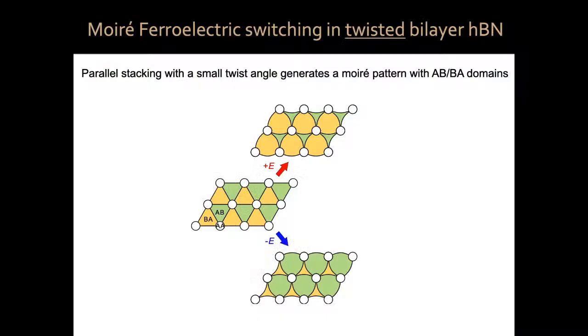If I twist them by a small angle, I can realize actual Moire ferroelectricity, where now, when I put a twist angle, I'm going to have these AB and BA domains similar to magic angle graphene, except that these now are very different. They have opposite electric dipole moments, those domains. And if I apply an electric field in one direction, I'm going to increase one type and shrink the other. And if I apply it in the opposite direction, I'm going to do the opposite.